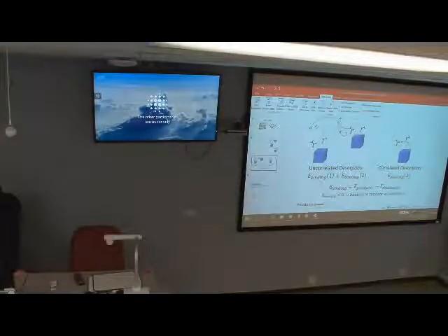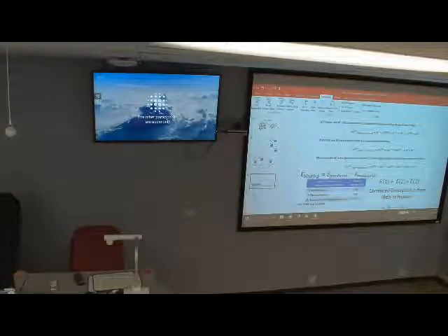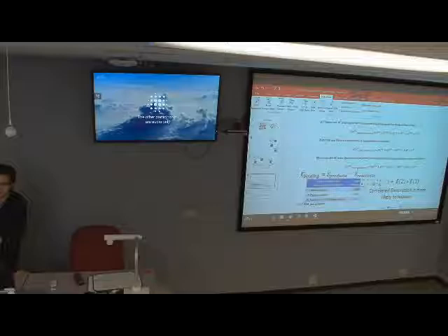And the last slide of results just summarizes everything I've talked about, and this table shows the binding energies for each of the calculations I showed. So this first one, removing the acetate ion and then protonating it, our DFT calculations showed that you get a negative binding energy. So it's actually more favorable for that acetate anion to be protonated and in solvent than being on the surface.